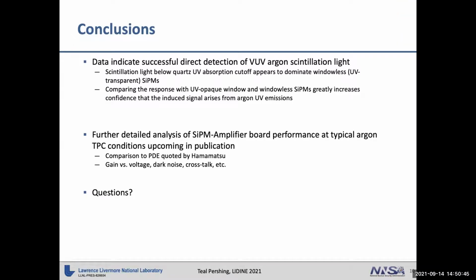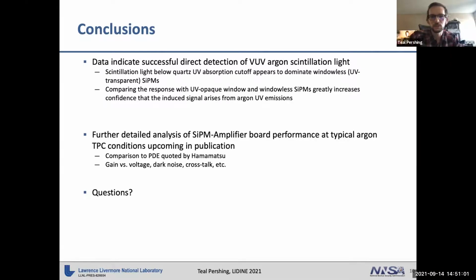I'm wondering what does windowless actually mean for that particular SiPM? Does it have any anti-reflective coating? Is it bare silicon with a layer of oxide, or something else? Do you know? Yeah. When we're referring to it as windowless, the Hamamatsu packages by default come with a quartz window in front of the silicon, so the main chip. And so we just took that front window off. Other than that, we haven't really done anything to the front of the SiPM to change it from what Hamamatsu provides commercially.